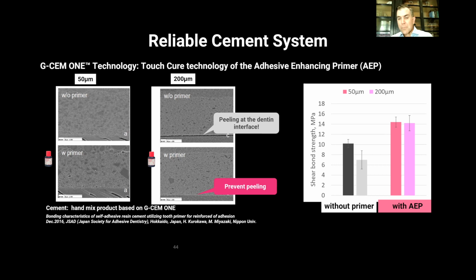So here we are. You can see 50 microns and 200 microns with the adhesive enhancing primer. You're going to have a very similar bond strength, only a slight decrease on that 200 micron. Without the primer, you can see a more drastic decrease, but you can also see that without the primer, the shear bond strength is less on the 50 and the 200 micron. It's just more pronounced on the 200 micron. So the point of this slide is to show that the adhesive enhancing primer increases the bond strength, and that's the bonding agent that we're discussing.